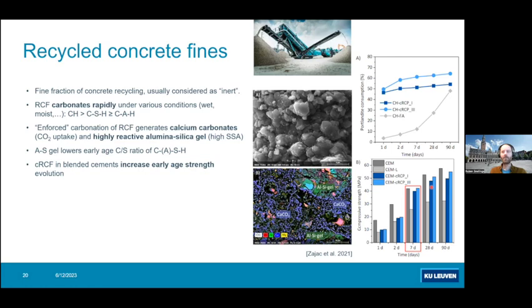And in many cases, when it's used, it's considered as inert. However, lately, researchers, for instance, from Heidelberg Cement, have intensively worked on carbonation of RCF, where using a wet or moist process, they were able to make calcium hydroxide, CSH, or calcium aluminate hydrates in the RCF react with CO2 to form calcium carbonate and silica or alumina gels, which can be highly reactive.